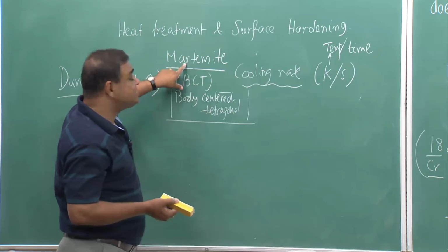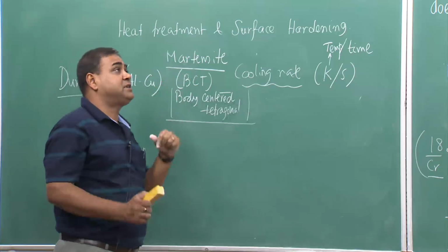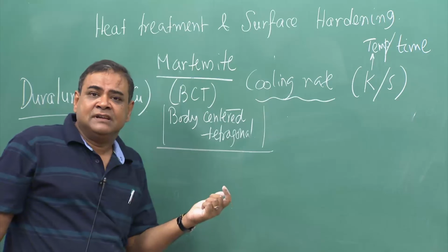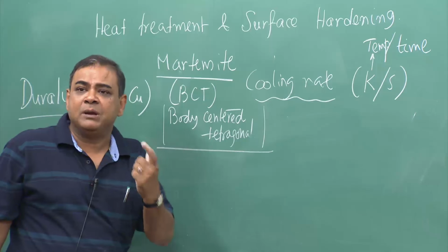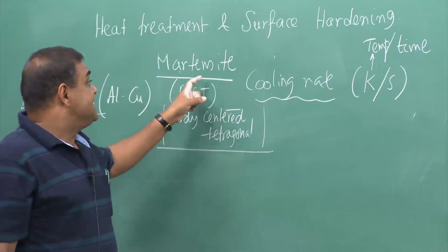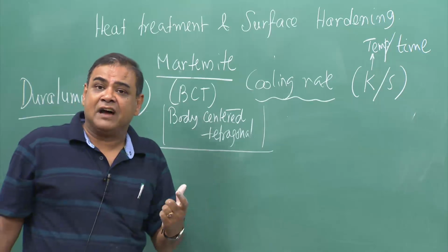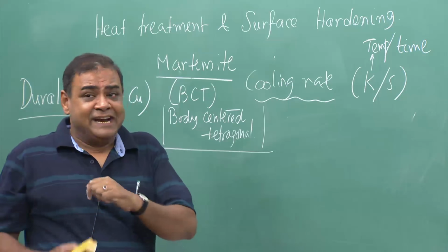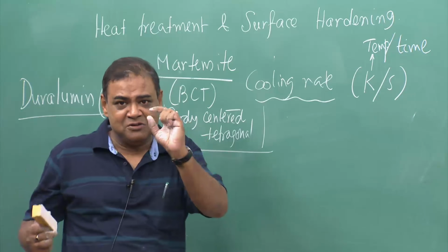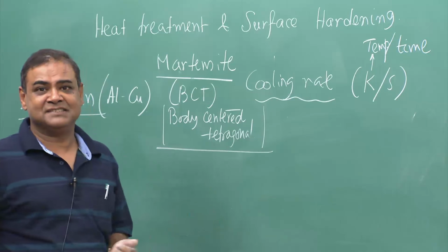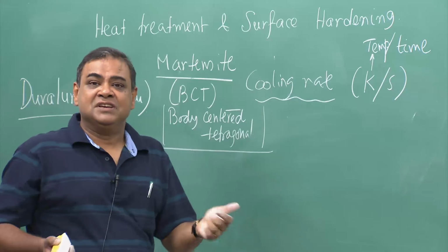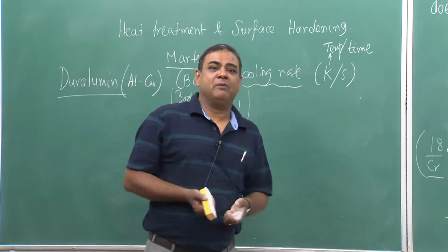But if we take this martensite to a little higher temperature, around 500 degrees Celsius, the martensite tempers and forms a phase called tempered martensite. That time it incorporates a little bit of ductility. Of course, the strength reduces a bit. It does not reduce much, but its ductility enhances. So, you can incorporate these properties into a cutting tool, so that we can have a longer performance.